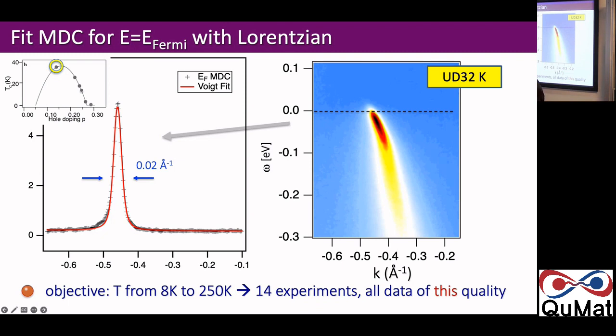Temperature is a horrifically expensive parameter to change at the synchrotron. You have to very slowly, gently warm up the sample. There's lots of hydrogen that has condensed onto your cryostat, and if you do that quickly, it will make what we call the hydrogen fart, which will kill your sample surface. So you have to be very patient. Then you have to repeat all these measurements again.